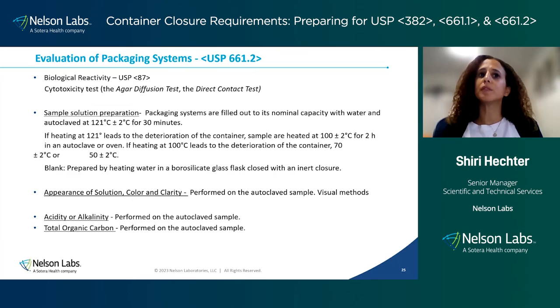The first test will be appearance of solution, color and clarity, and they're performed again on the autoclaved samples. The sample extracts are observed against water and against the reference system for clarity and color, and they should be at least as clear and colorless as water. Acidity, alkalinity, or total organic carbon. We touched on those two tests before. They're similar tests as I described before, but they do specify, in this case, we're using the autoclaved sample.